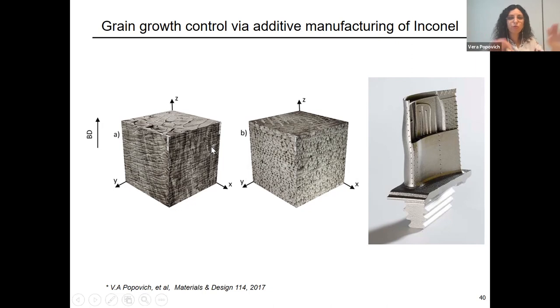And this is an example of two distinctly different microstructures, where we can control the grain growth, yeah. So this is elongated along the build direction. This is 001 orientation of grains. So you can see those elongated grains. It's a 3D representation of the structure. And these are the equiaxed grains. And you can clearly see what we call a fish eye structure. Yeah? So this is the melt pool. So this is how each layer is molten, yeah, and put together.